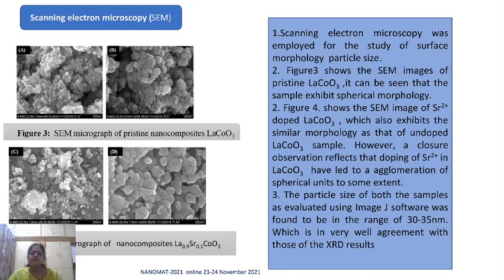If we observe it closely, then you can see that there is agglomeration of the particles. Further, the particle size of both the samples was evaluated by ImageJ software and was found to be in the range of 30 to 35 nanometer, which was in close agreement with the result obtained from the XRD pattern.